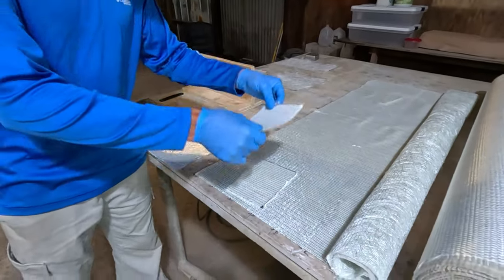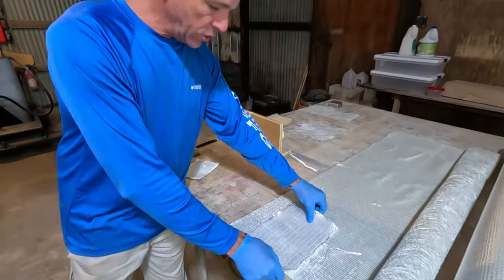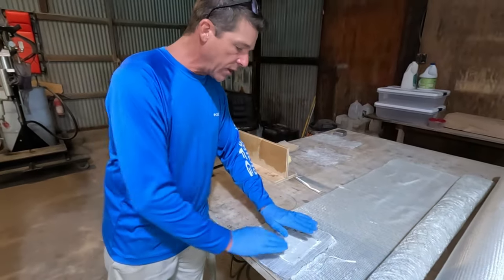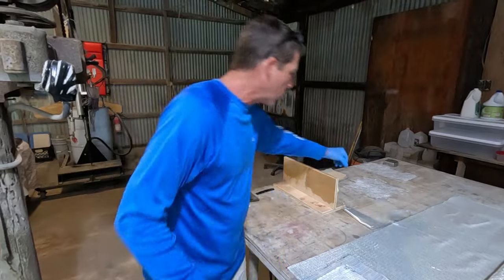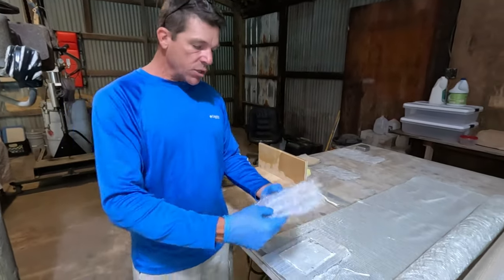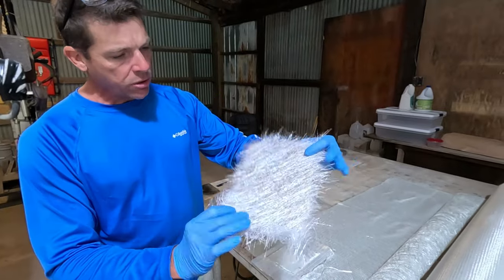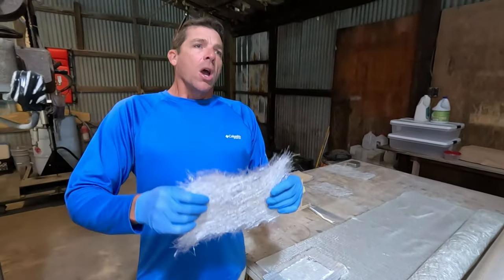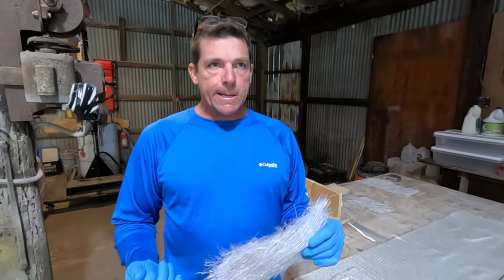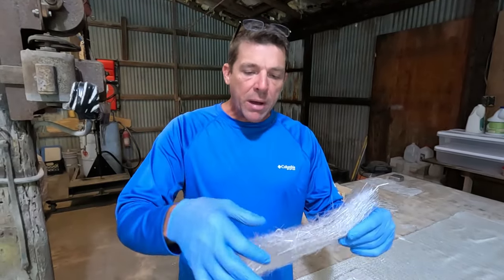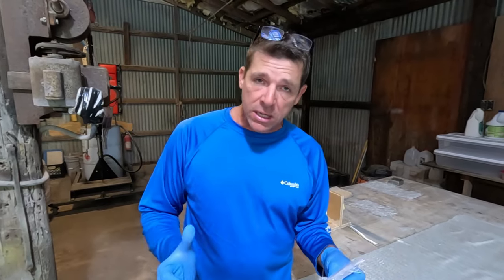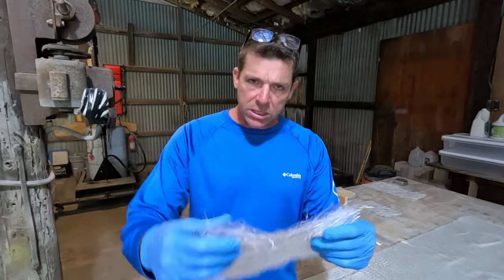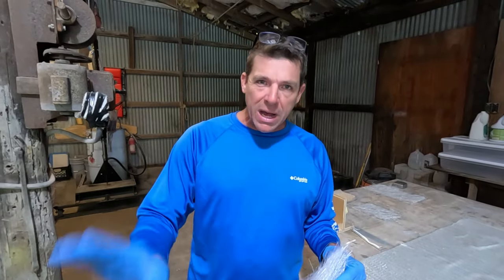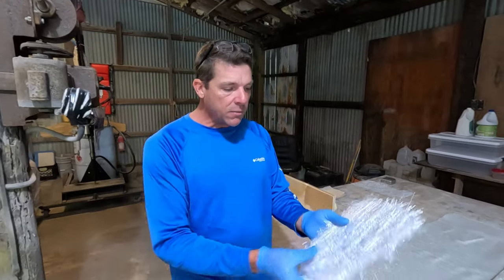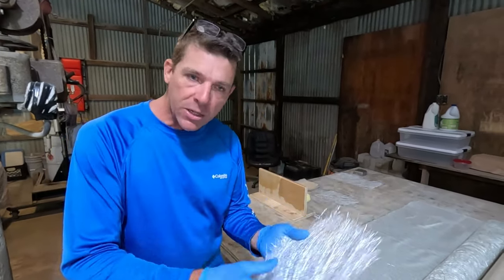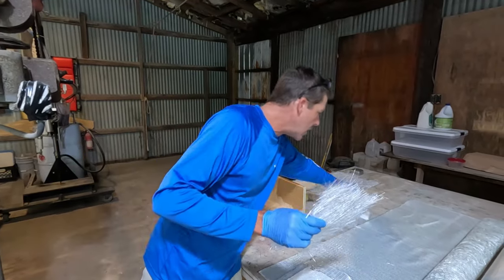If you want to laminate this, you could put a layer of 1708, a layer of the 1808, a layer of the 1708, and continue to stack those, and it would work out beautifully. At the end of your laminate schedule, if you wanted something with a nicer cosmetic, you could use just some straight CSM. I don't recommend using this typically with epoxy. You can in certain situations, but epoxy does not have styrene in it as a solvent, and it will not melt and make the CSM conform like polyester and vinyl ester resins will. So I typically recommend using CSM with vinyl ester and polyester, not so much with epoxy, although it can be done.